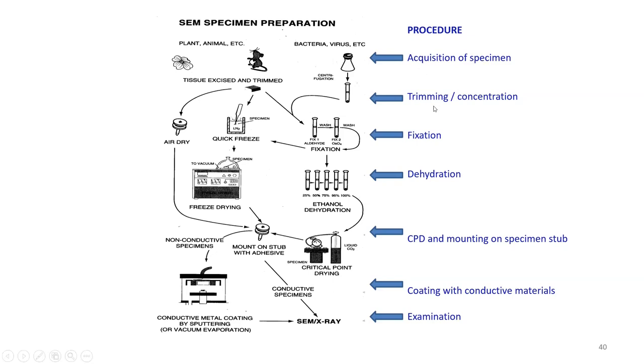So you acquire your specimen, you do your trimming, then you fix. Fixation is always similar to that of TEM. Dehydration, till here it's the same. Then a special step comes in for drying, a special procedure called CPD, or critical point drying. This step is done to avoid the surface tension effects. If you perform normal air drying, due to surface tension effects, the cells of the tissue will shrink, right? It'll be dehydrated and it'll shrink, but that is not something you want.